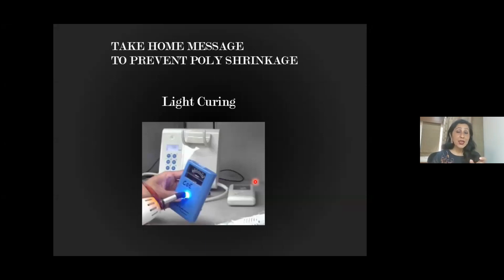So your light cure should be focused. Your light curing machine should have this wavelength and should also have the right intensity, because if your light cure probe does not generate good intensity, then you are just using it for no other reason. It is just the light is being produced and nothing is happening inside, my dear friends. You feel that your curing is taking place, but actually no cure is taking place. Very little cure is taking place, and lots of unreacted monomers are still in your restoration, which will lead to polymerization shrinkage, which will lead to marginal deficiencies at a later date.